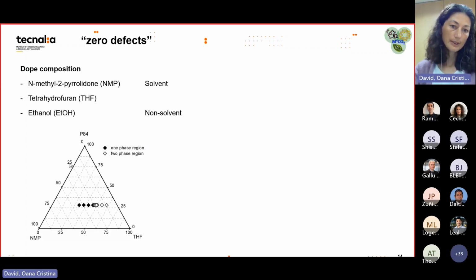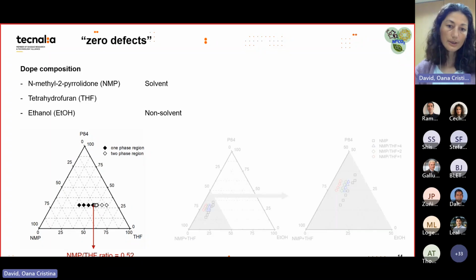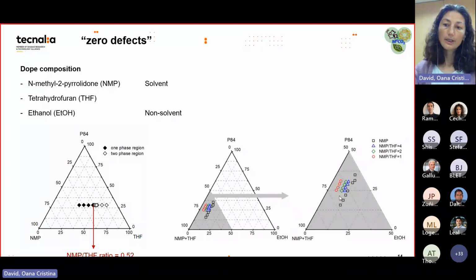So the first study was to determine how much THF we can add to NMP. And here we saw that there is a separation, a coagulation, if we have this minimum ratio of NMP to THF of 0.52. And then the next study was to see how much ethanol we can add as well in this dope composition, the non-solvent, to be closer to the boundary. So this is what we did.